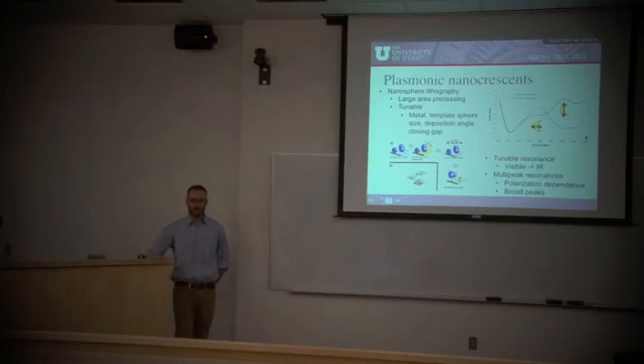Another thing to note is that the intrinsic interaction with light is important here. If I change the size of these nano crescents, I can change the wavelength of light. If I make this nano crescent larger, the light will go more towards the red, towards lower energy, whereas if I make them smaller, they will go towards the blue light. I can tune the properties of this light just by changing the size and the shape of these nano crescents.